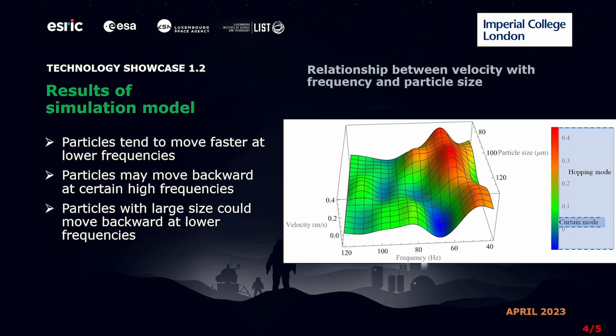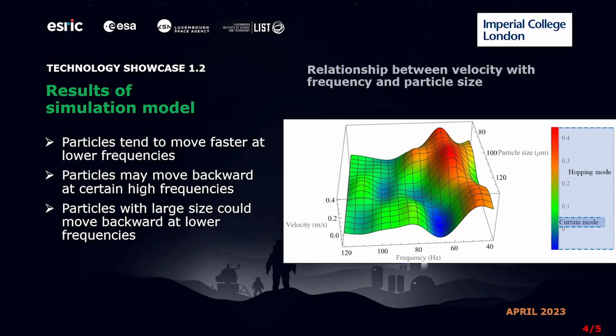From the plot, we can see the relationship between particles' movement velocities, their particle size and the operating frequencies of the system. The z-axis is the movement velocity. We can see that at lower frequencies, particles tend to move faster. Also, at a critical frequency like 60 Hertz, some particles may move backward. For the deep blue part, the particle has negative velocity, so big particles move backward. For small particles, in the red part, small particles can move very fast in the forward direction.